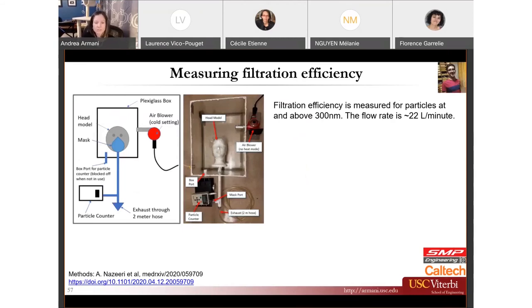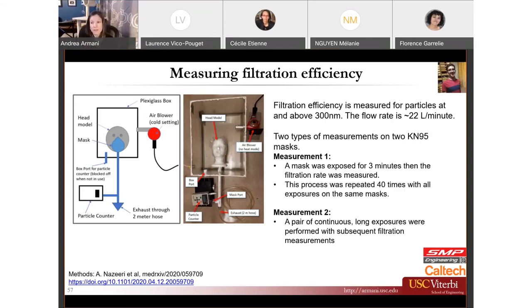So how this works is they take a mask, they mount it on a dummy. They actually put a wax seal around the edges of the mask, and that makes sure that no particles in the chamber can sneak in the sides. They flow in particles of a fixed size. They chose particles at and above 300 nanometers for this test. And they have a specific flow rate. In this case, they use 22 liters per minute. So pretty fast, really trying to force the particles into the mask.